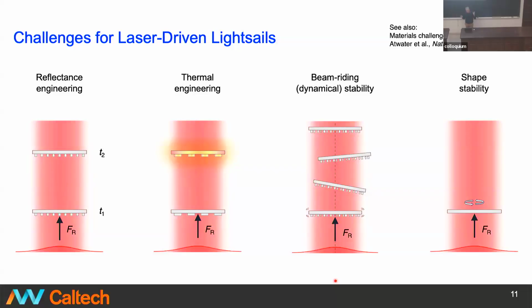So you could use some higher order beam. People proposed using donut beams and shaped sails and all sorts of things. But that turns out to be a big challenge. So we spent quite a bit of time thinking about how to design something that could exhibit beam riding stability. In other words, if it had some instability, it could self-correct and actually maintain a metastable trajectory along the optical axis.